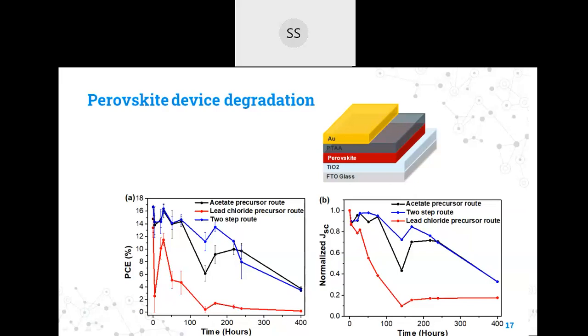Yes, you can change the thickness, but it won't help much, because once the moisture has reached the perovskite film, it won't take long to degrade the perovskite. If you have more thickness, it will take a little bit higher time to degrade. Suppose you are taking 10 days to degrade the efficiency from 15% to 8%, it will take 17 or 18 days, because with the higher thickness your efficiency will already be a little higher, and it will take a little extra time. But it won't add much significance in improving the stability of the perovskite. Okay.